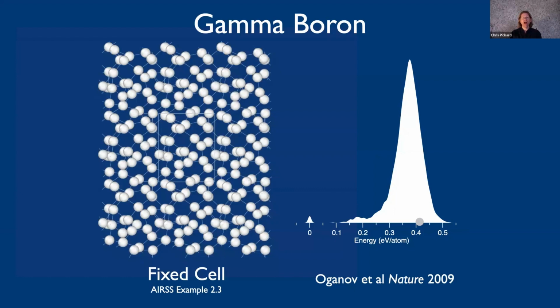But I'd like to just show you an example here. The code that I'm mentioning now, the AIRSS code, the ab initio random structure searching code, is available under GPL2, and you can download it. There are a bunch of examples included in that distribution. The 2.3 example is this one here, where a known unit cell had been determined for a high pressure phase of boron. The diffraction pattern had been indexed, but the arrangement of the atoms inside the unit cell was not known. This was first done by Artem Oganov, who's also working in crystal structure prediction. So we don't know where the boron atoms are, but we know the shape of the box.